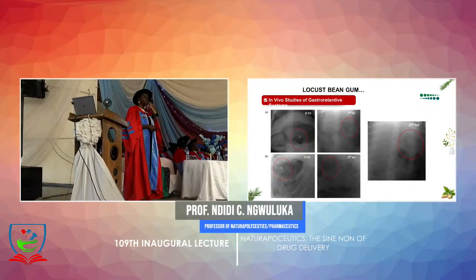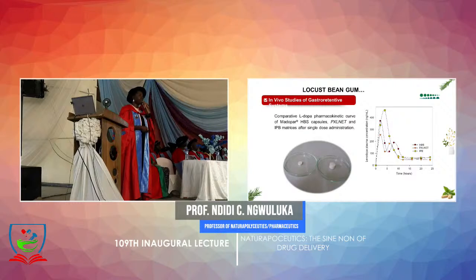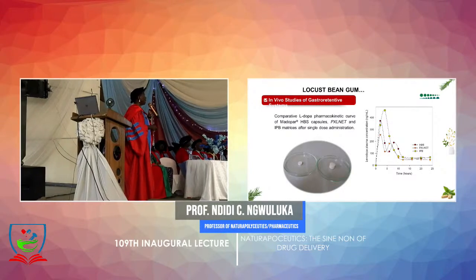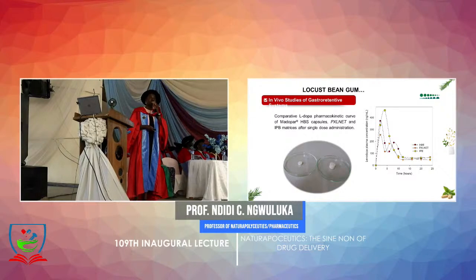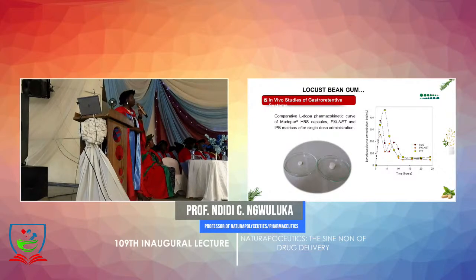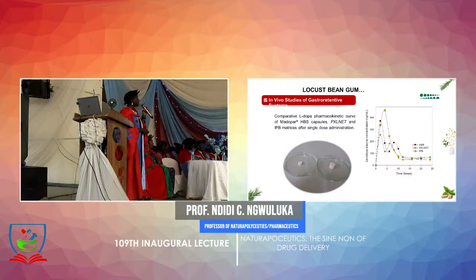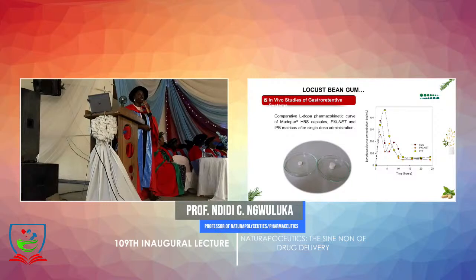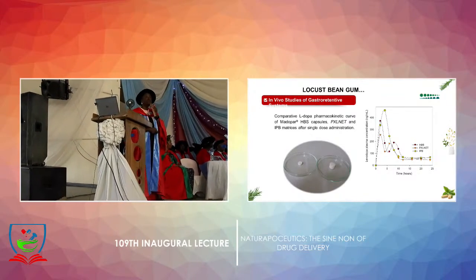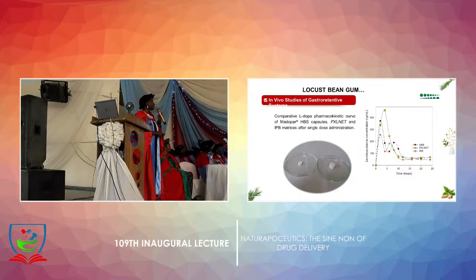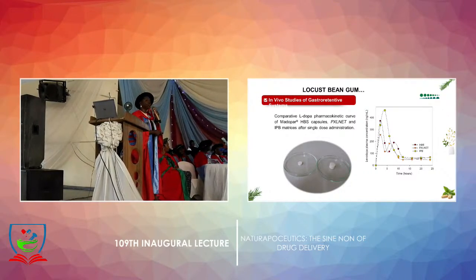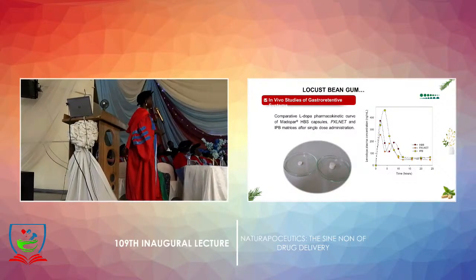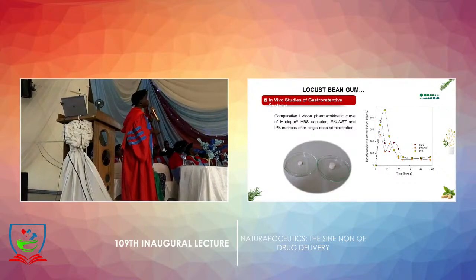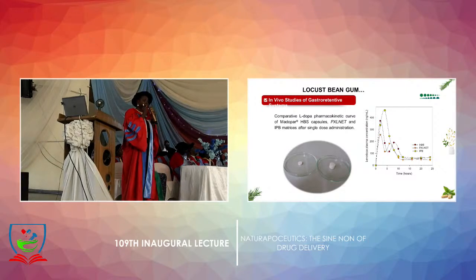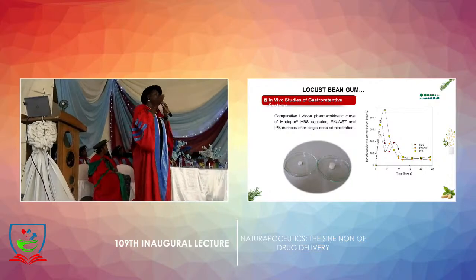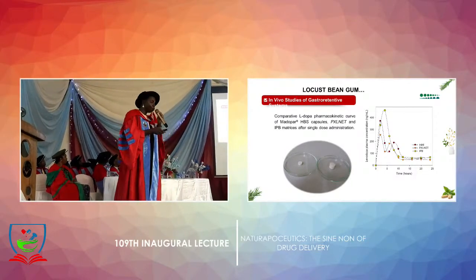So we didn't just run the animal studies with only our tablets. We also tried to use what is currently available. Madopar HBS capsule uses a floating system to ensure gastro retention. This capsule is made by Roche, a pharmaceutical company, for management of Parkinson's disease. So we ran this, and these are the blood samples, the concentration of the drug in the blood. When you look at it, you see that the one that contained the nanoparticles behaved not too far from this. But the difference was that the one with nanoparticles actually had more of the drug in the cerebrospinal fluid, which was a really good result.